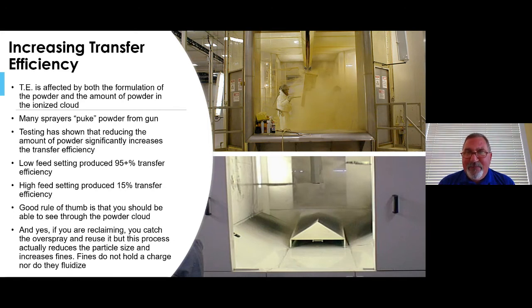And so reducing the amount of powder coming out of the guns really significantly impacts the ability to get a higher transfer efficiency. You can see there that the low feed setting in our laboratory testing showed that we could get 95% plus transfer efficiency. When we turned the feed pressure all the way up, it was about 15%. So in our case, 15% of the powder was on the part. The other 85% was on the floor. So you should be able to see through a cloud.